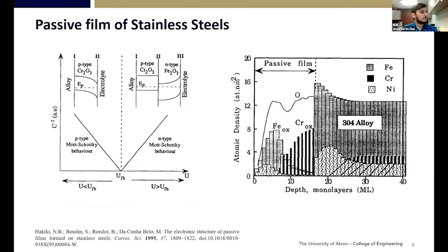So by the Mott-Schottky theory, if the potential that we have on our rebar is above the flat band potential, the passive film will have this double layer of the chromium and iron oxide having the p-type and n-type respectively. However, if we are below this flat band potential, only the chromium oxide will be formed.